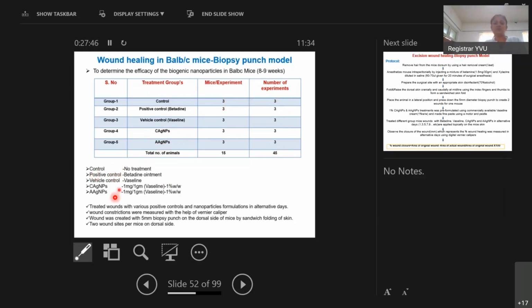So the control group had no treatment, with positive control betadine and vehicle control vaseline groups. For CAGNPs I prepared a 1% weight by weight formulation, 1 mg per 1 gram vaseline, and AAGNPs likewise 1 mg per 1 gram vaseline, 1% weight by weight. The wounds were treated with the various positive controls and nanoparticle formulations on alternate days. The wound constrictions were measured with the help of a vernier caliper. The wound was created with a 5 mm biopsy punch on the dorsal side of the mice by sandwich folding of the skin. These two wound sites were on the dorsal side of the mice.